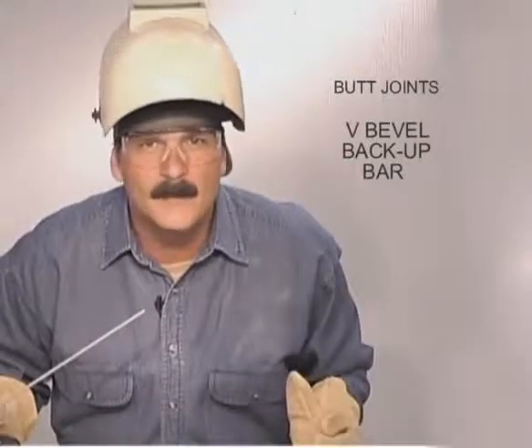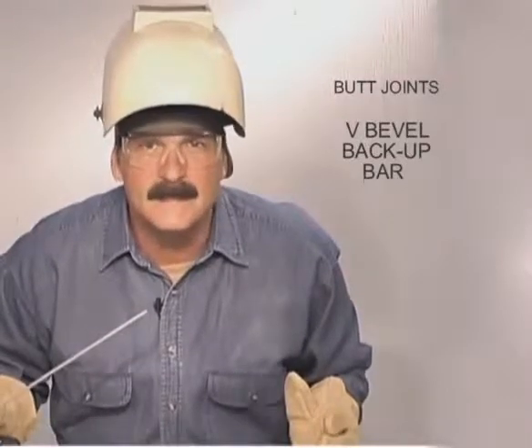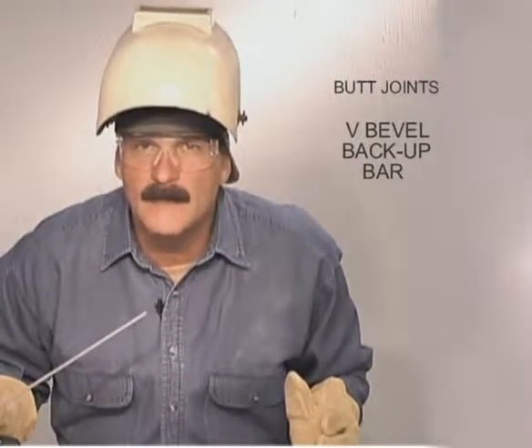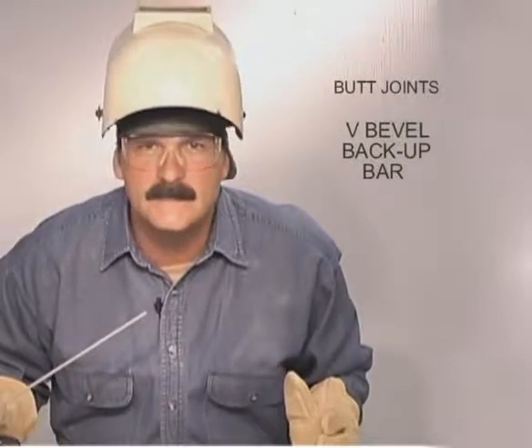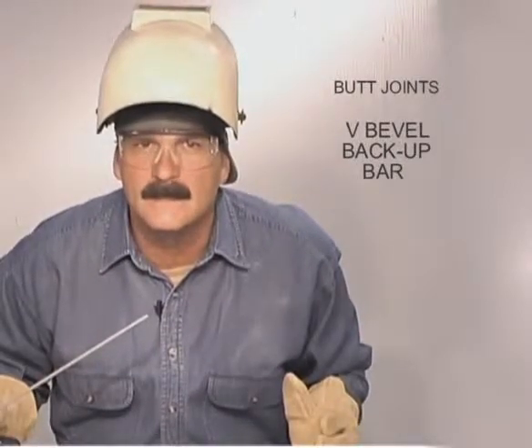Travel up fast enough to keep the metal from overheating, which causes the molten puddle to spill down. You may need to lower the amperage a little, maybe 5 amps or so, but don't lower it too much, as many problems are caused by running too cold on verticals as by running too hot. Remember, the amperage only provides the heat. It's the travel speed, rod angle, and arc gap that determine just how hot the metal is going to get.